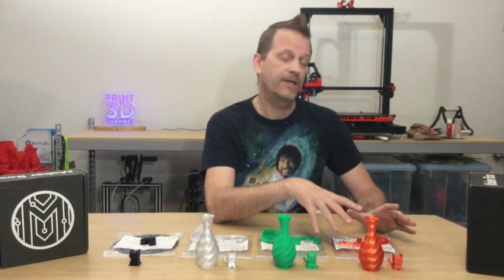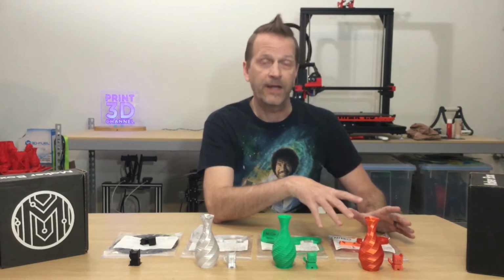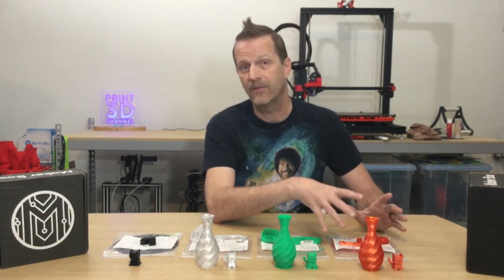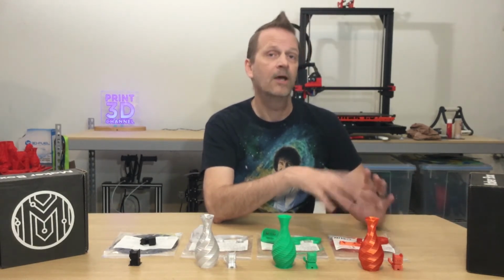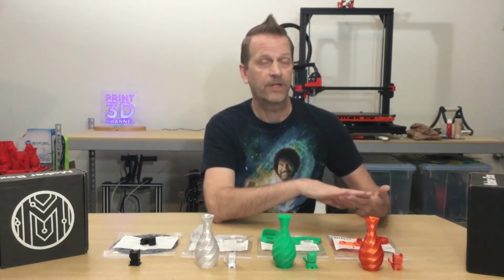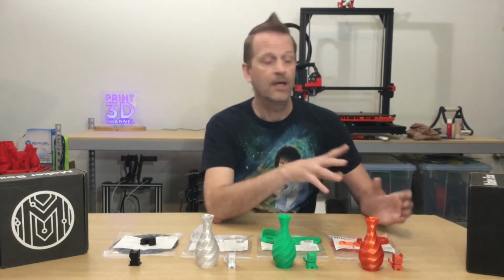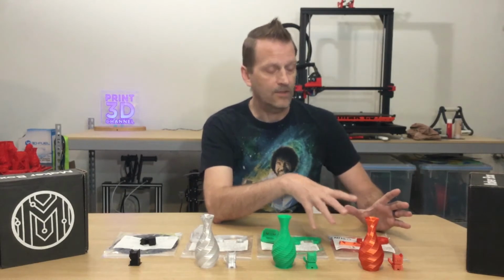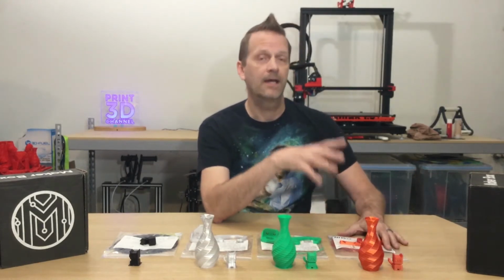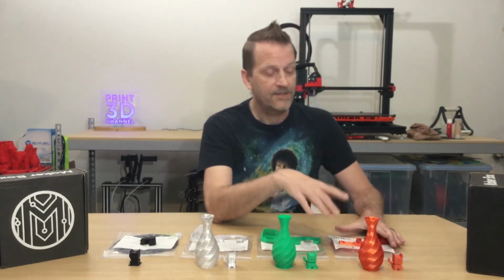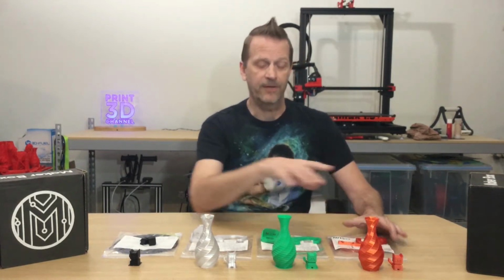The temperature range that it advertises is 190 to 220. I sat at 205 and had no problems whatsoever, with minimal stringing, really good layer adhesion, and really good first layer and top layer look. So I recommend this eSilk Jacinth from eSun. Again, this is in the October MakerBox, but this is a really cool filament to play with.